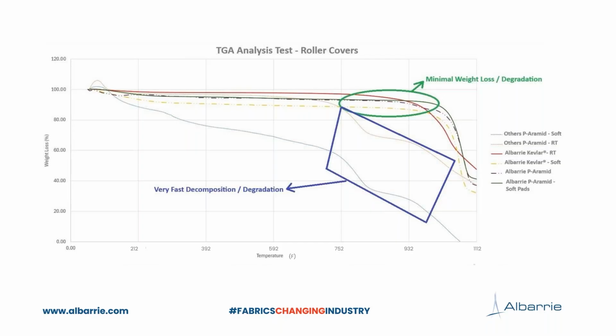In stark contrast, the line marked "the others," para-aramid soft and resin treated, the two gray dotted lines, degraded rapidly, starting at 212 degrees Fahrenheit for the soft and 752 degrees Fahrenheit for the resin treated, losing almost all their weight by 1076 degrees Fahrenheit. This steep decline is a clear indicator of poor thermal stability.